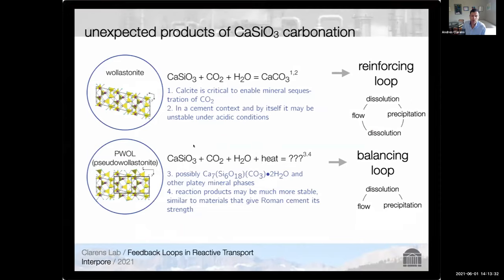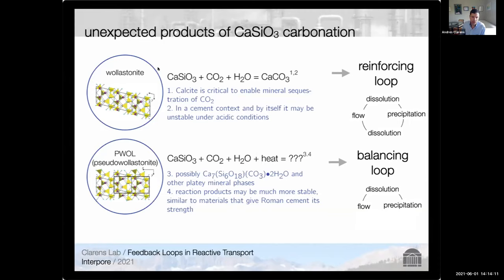The chemical system we've been concentrating on is that of the model calcium silicate wollastonite and pseudowollastonite, which has the same chemical formula CaSiO3 but a different crystal structure — so they're polymorphs of one another. It turns out that even though they have the same chemical formula, when you react them under different conditions you get very different products. Many of you may be aware that when you carbonate a silicate you tend to generate carbonates as products, and those carbonates can subsequently re-dissolve if exposed to an acidic solution such as water or brine with CO2 in it.